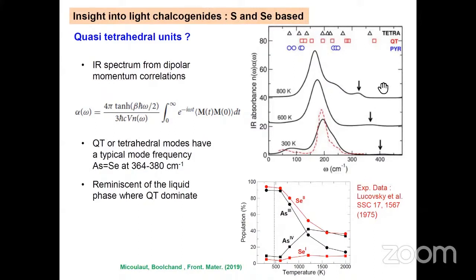And as you can see, that amplitude grows with increasing temperature. And this might, in fact, be compatible with the population of arsenic 4, which increases as you increase the temperature. And around 1,000 degrees, that fraction is about 40% for arsenic 4. It's, of course, a minority population at room temperature in the glass, which is less than 10%.